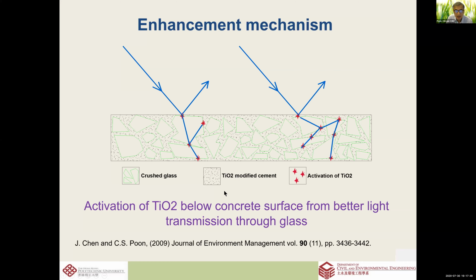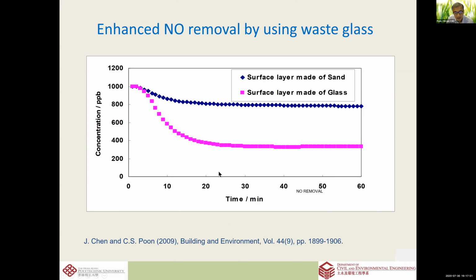So this is to show the surface layer without glass. This is the surface layer made with sand. This is the surface layer made with glass, and that is the photocatalytic removal. This is 1,000 ppb. It could reduce, in laboratory conditions, to about 300 ppb. This is 70% removal for this particular sample.